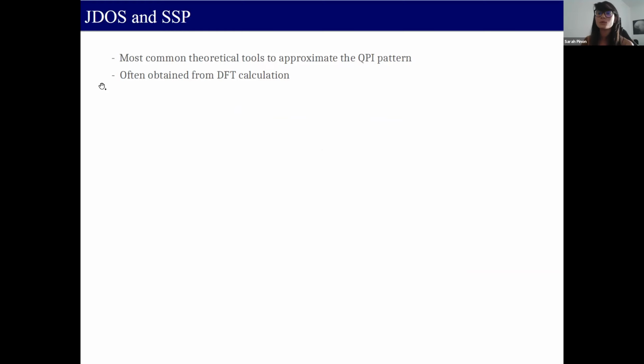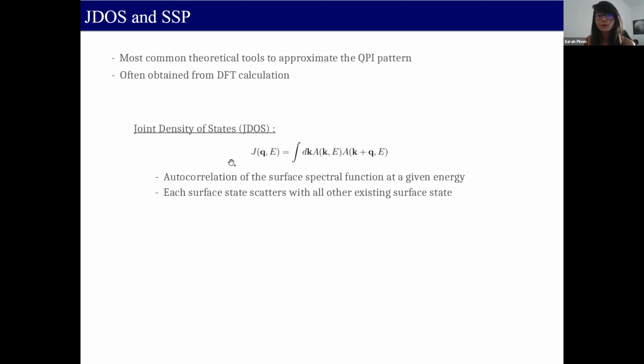So theoretically, to approximate the QPI pattern, there are two common tools called JDOS and SSP, which are often obtained using a DFT calculation beforehand. So the first one, the joint density of states, is computed using this formula. Basically, we do an autocorrelation of the surface spectral function at a given energy. Physically, what this means is that we consider that each surface state scatters with all of the other existing surface states that have the same energy. So in the equation, this is seen as taking the surface spectral function at a momentum k and energy E, and then the surface spectral function at another momentum k plus q, and then we integrate over k. So we take all of the existing surface states at a certain energy E.